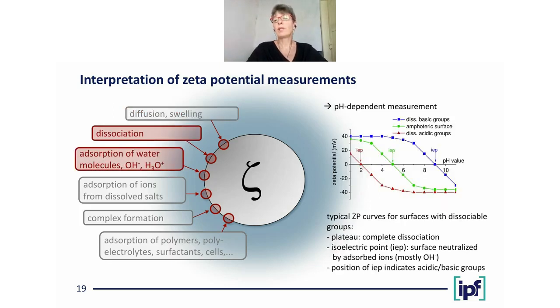What we mostly do are pH-dependent measurements. Here you can see typical pH-dependent Zeta potential curves for different kinds of surface functionalities. An important parameter is here the so-called isoelectric point, the zero crossing of the Zeta potential. If the isoelectric point is very low, below pH 3 approximately, then we know we have acidic surface groups. If the isoelectric point is above pH 7 or 8, we have basic or alkaline groups on the surface, and if it's somewhere in between, we have either an amphoteric or an uncharged surface.